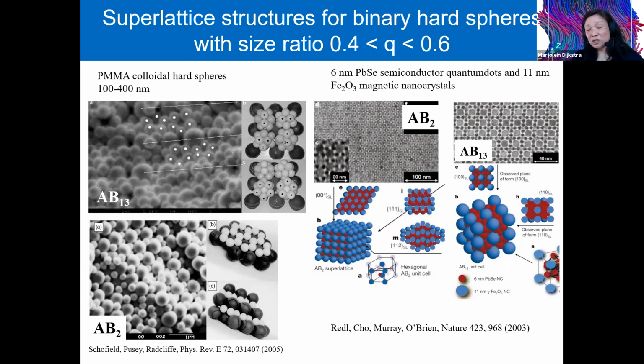It's a stacking of hexagonal planes of big spheres, and then a Kagome lattice of small spheres, and then a hexagonal layer of big spheres. And it's an alternating sequence of big spheres, small spheres, big spheres, small spheres. And these crystal structures have been obtained in the bigger colloidal particles, but also in the nanocrystal suspensions. And again, all these very exotic crystal structures are purely entropy driven.